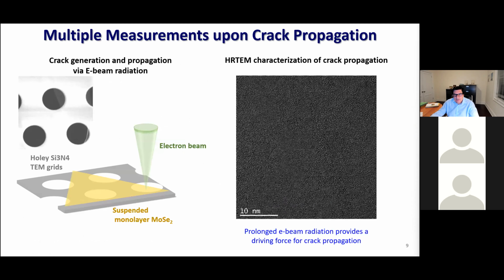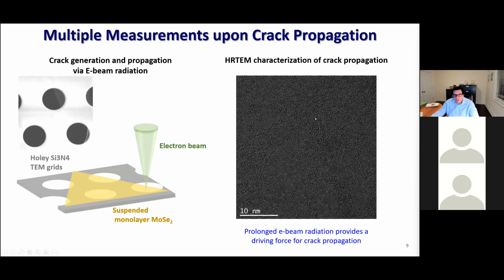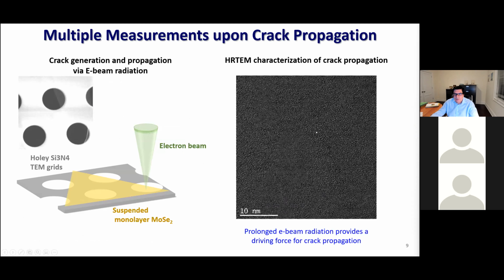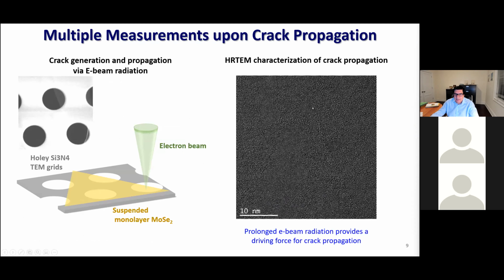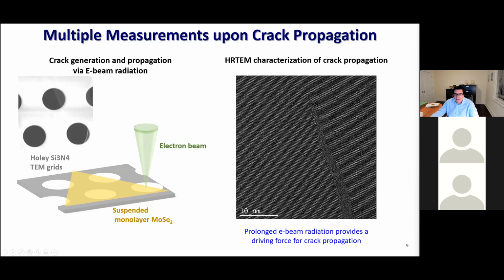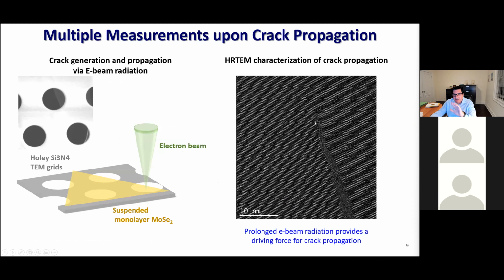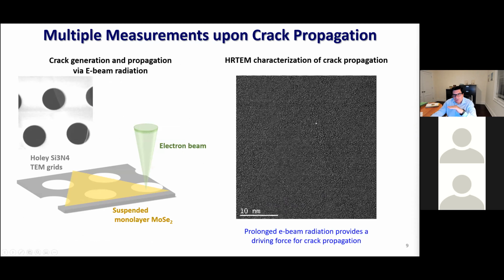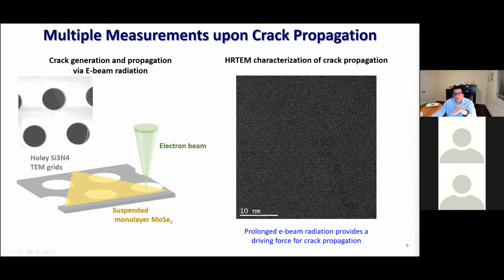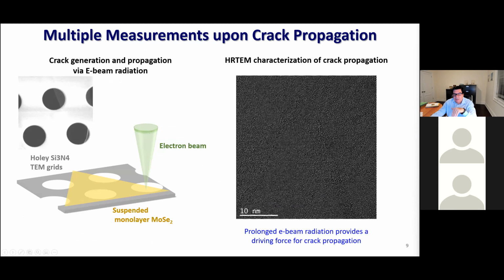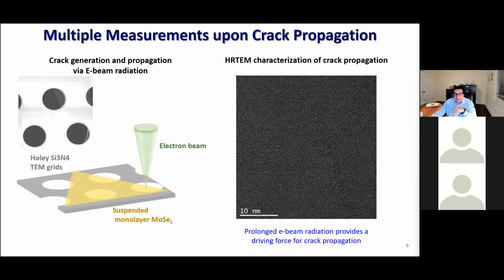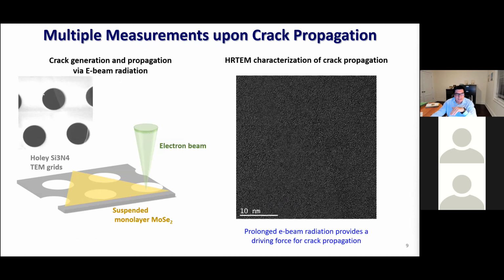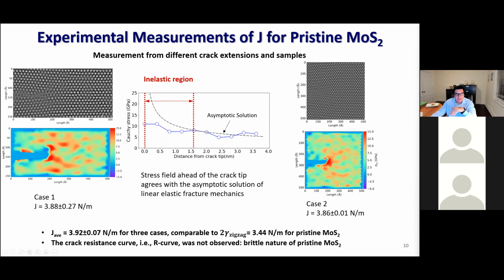This is showing that if you control the electron beam and the dose, you can propagate cracks. And so the idea is that you propagate the crack and you do an observation with limited dose to avoid any further propagation, because the interest is in having a stationary crack and map the fields with the methodology that I just explained, and then compute the toughness.